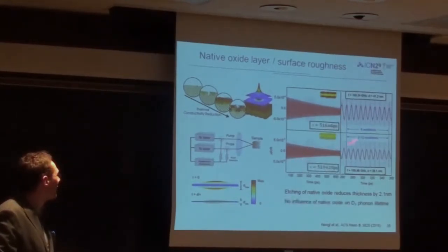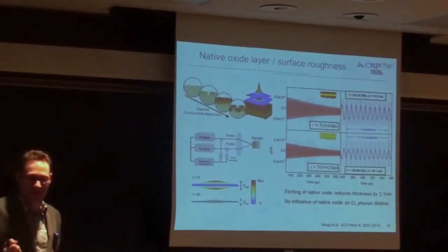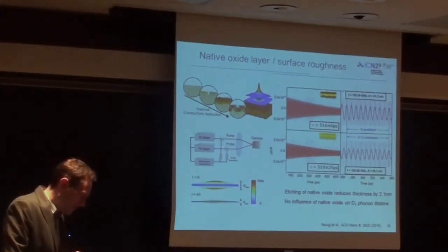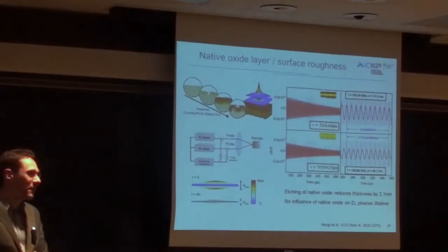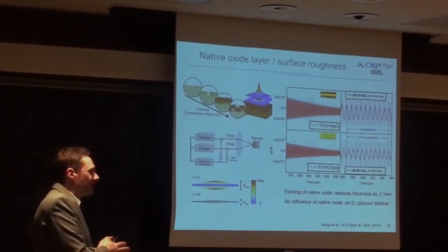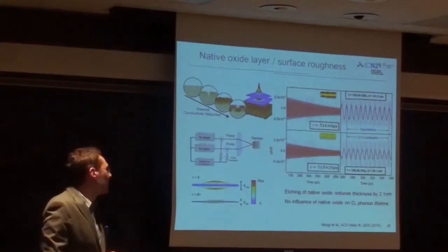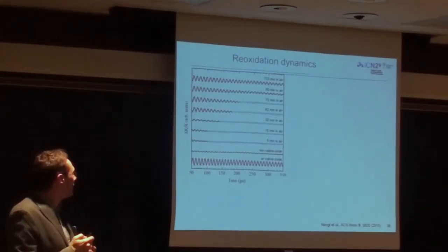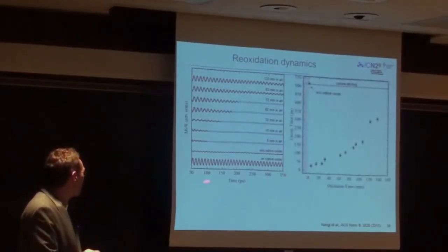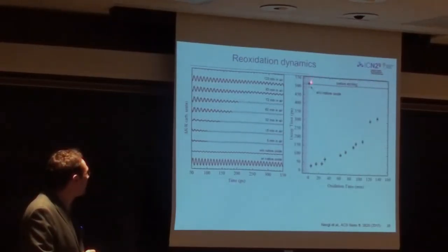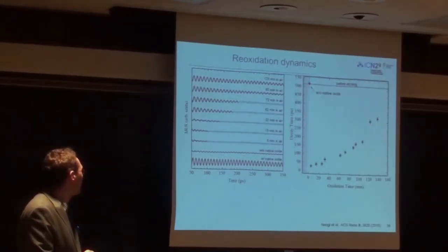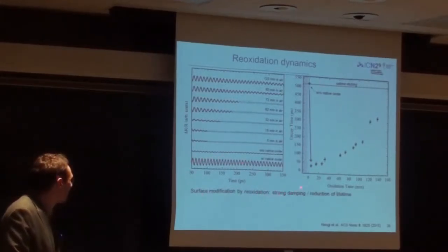And the other thing that you see is that the lifetime in both cases is the same. So apparently, the presence of the native oxide is strongly affecting the thermal properties, however, it is not affecting the dynamics of the gigahertz phonons. So what you can do is follow the reoxidation dynamics. We've done this here for the native oxide. We start from 500 picoseconds acoustic phonon lifetime. We remove the oxide, you get the same value, and what you can see then is when you open the